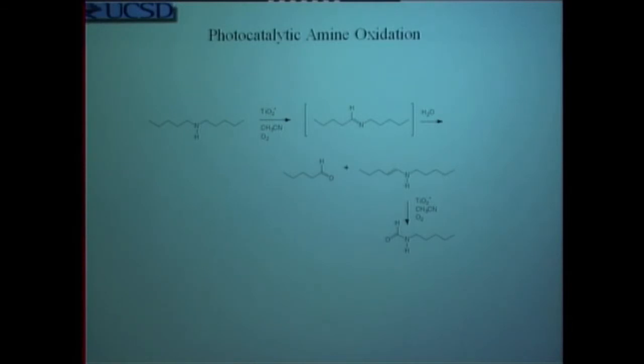You see the nitrogen atom in the center of this molecule. After oxidation takes place, a cation is formed by giving up an electron from the original starting material. The oxidized species is then exposed to oxygen, typically in acetonitrile solution, giving an intermediate which splits apart, and you can see that the products are simpler. They've induced chemical cleavage by using an absorption of a photon on an irradiated surface.